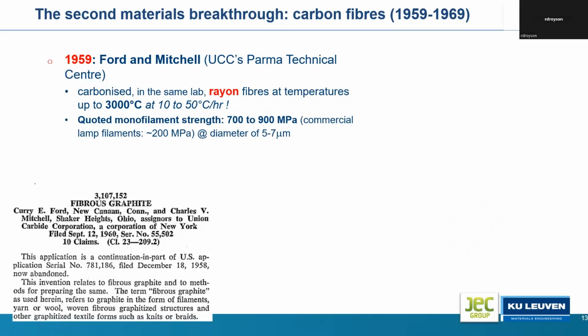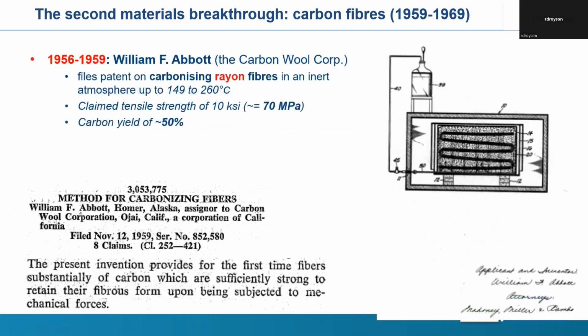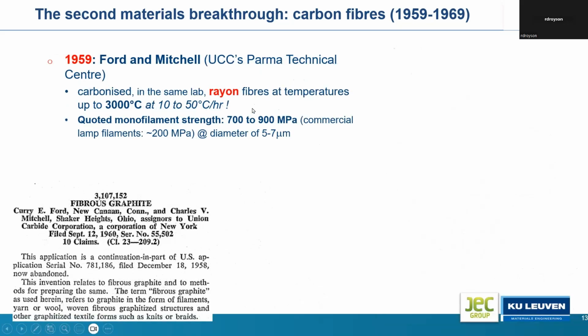And then we go back to Union Carbide, and in the same group as Bacon, Ford and Mitchell then improved that approach, the previous one of Abbott, where he only was heating up the rayon fibers to 260 degrees. They were doing it up to 3000 degrees. And they were reaching monofilament strength of up to 900 megapascal.